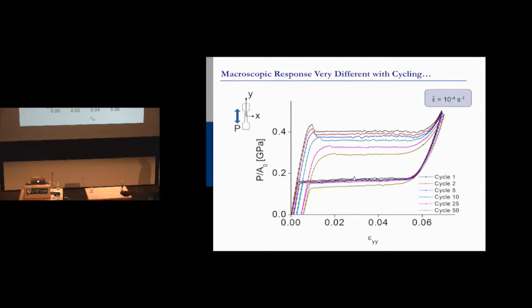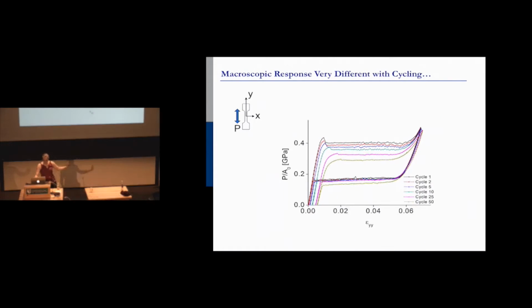And you can see that when you're cycling, you really change macroscopically a lot what you're doing. Not so much on the back end, but very much on the front end. So as you're cycling, it becomes easier to nucleate transformation, and it kind of doesn't last as long. You start to get some additional stuff going on. So, okay, macroscopically things change a lot.